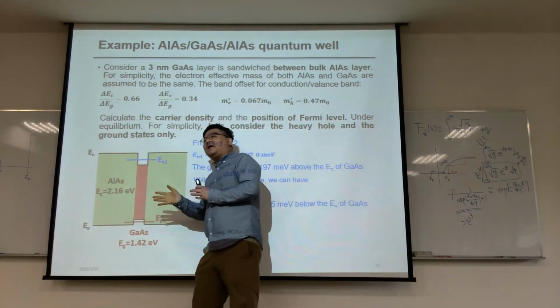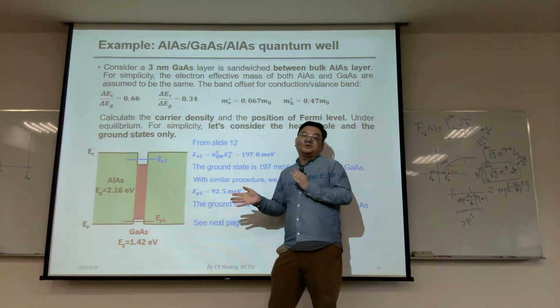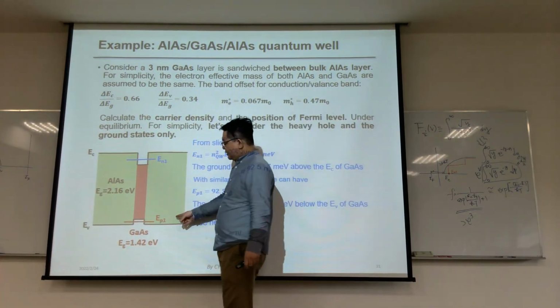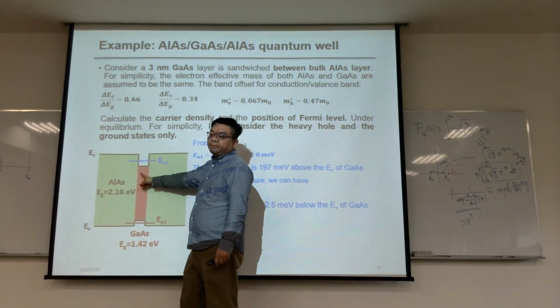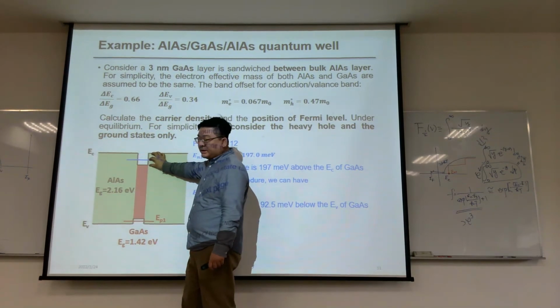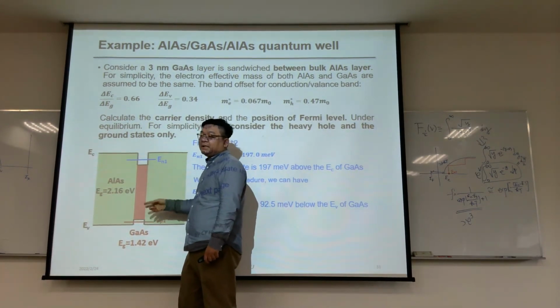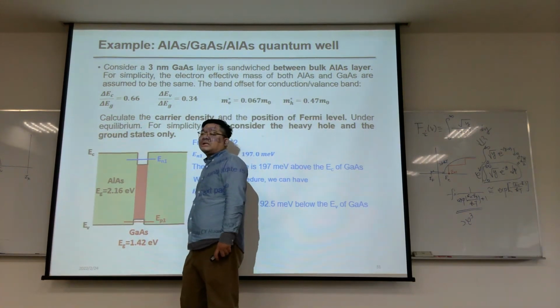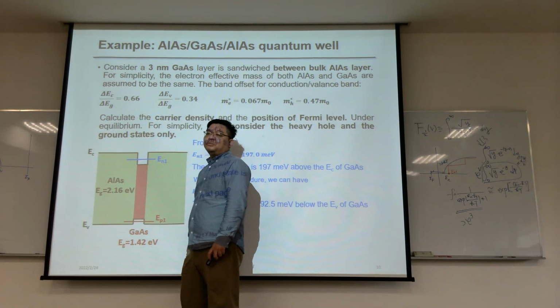The band edge absorption of such a quantum well will blue shift compared to its band gap, and the difference will be the ground state energies. So this is the quantization effect of the quantum well. The absorption edge will blue shift.